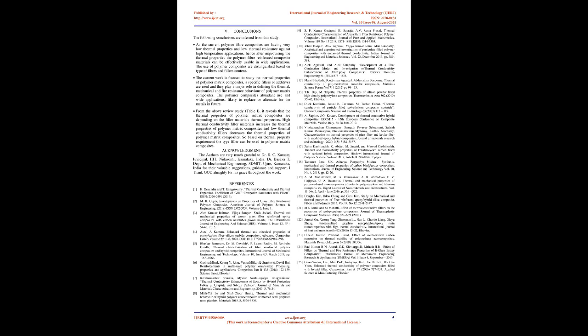23. Hybrid composites are prepared with epoxy resin, glass fiber, fly ash, stone powder, and silicon carbide in a 50:50 matrix fiber and 5% and 20% fillers in weight proportion. From thermal experiments it is observed that glass fiber epoxy resin, GFER, and silicon carbide 5% and GFER plus silicon carbide 20% shows high thermal conductivities compared to other composites, but GFER and fly ash 5%, GFER and silicon carbide 20% and GFER and stone powder 20% exhibits low CTE when compared with other composites.